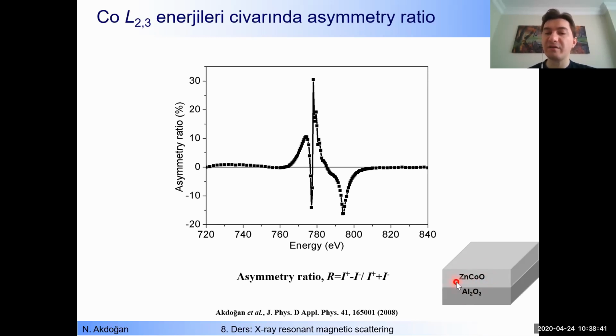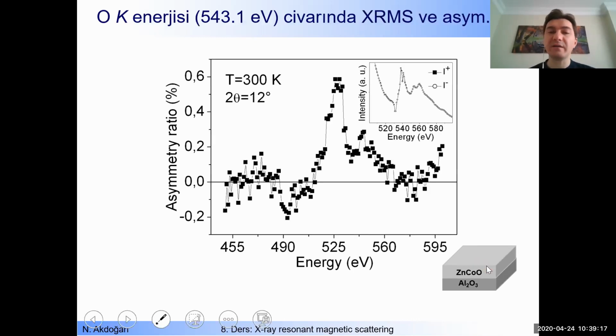But I would like to be sure, and I will investigate both oxygen and zinc elements because this method is very useful. This is element specific, okay? If you consider other conventional magnetization measurement systems, magnetometers, you can only measure the magnetization of the whole system. But by using the XRMS method, I can selectively measure the contribution of each element to the magnetization. So then let me do that.